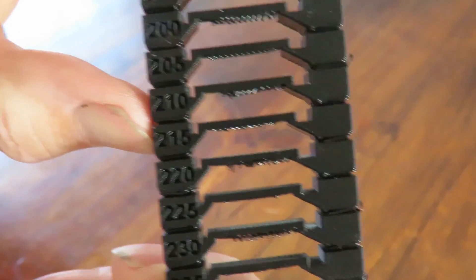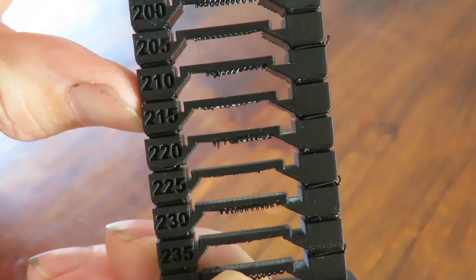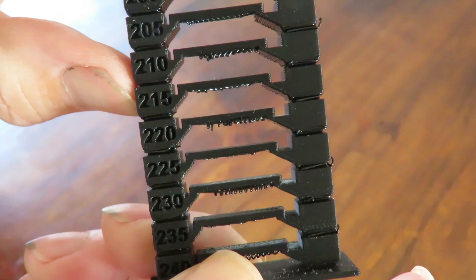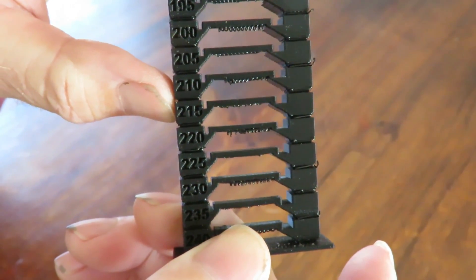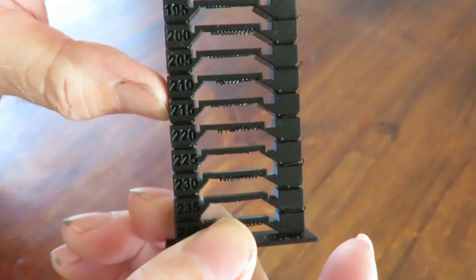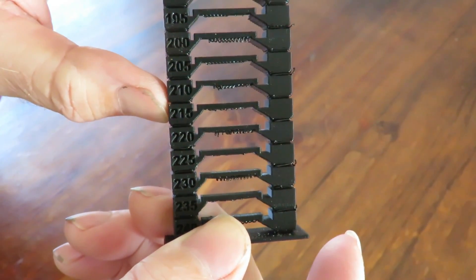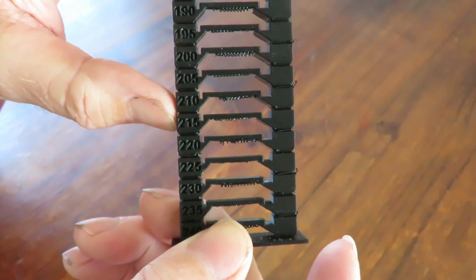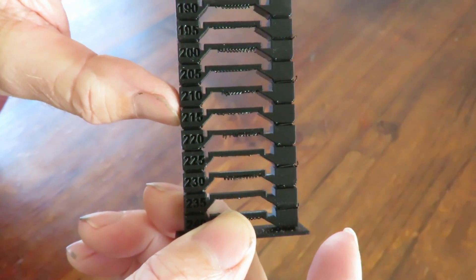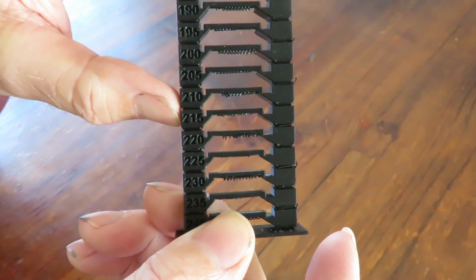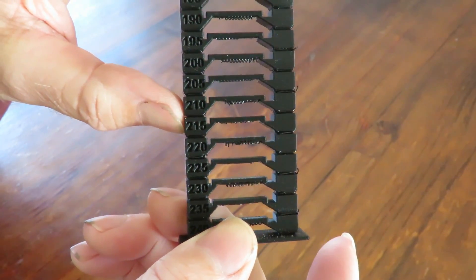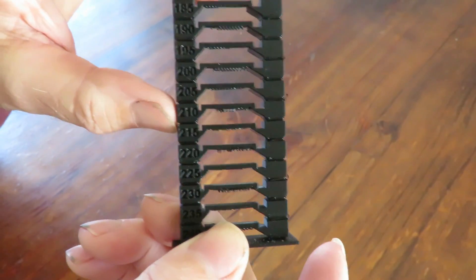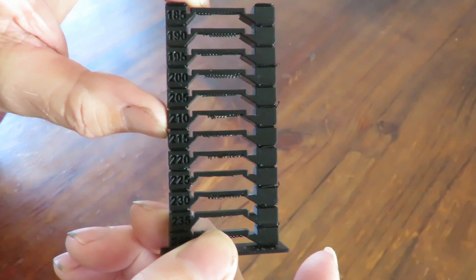This method will work on any printer at all, and I really recommend that you actually print out at least one temperature tower per new spool so you know the range you're going to be printing at rather than waste a heap of plastic thinking you've got the range set correctly. You might get separation between the layers because the temperature is too cold, or you're getting lots of stringing because it's overheating. So it's important to get it set at the correct temperature, and this is the only way to do it properly.